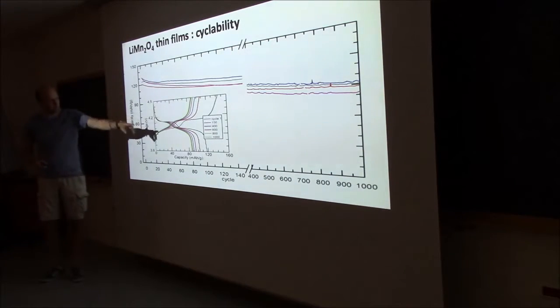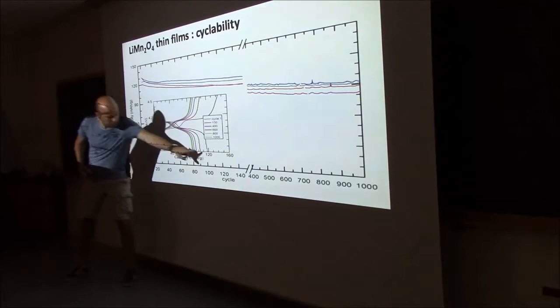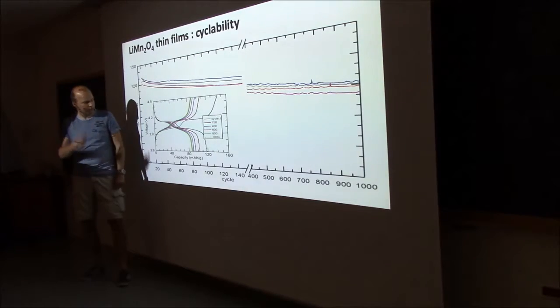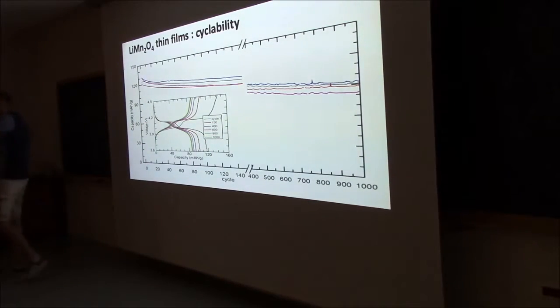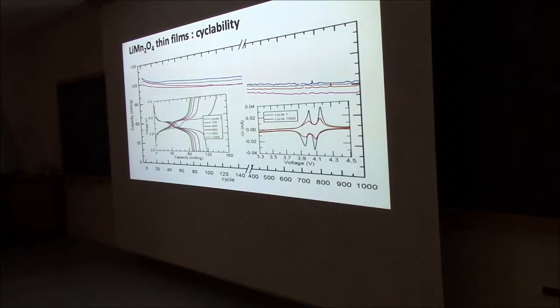Now for these materials, if you cycle them, you can see the discharge capacity goes down over time, which is normal, that's what you see there, but you can see the plateaus are not changing. So always the same voltage that you're taking out. And you can also see that in the CV measurements, where the first cycle had a very strong peak, the other side of the peak dropped somewhat, but you can see it didn't move, so the internal resistance wasn't changed. I'm not showing it over here, but we also do a lot of electrochemical impedance spectroscopy, so that you can study your system and you can really extract all the different components which are contributing to the impedance, from the ionic conductivity, electroconductivity, all the different things, which is not simple. You can do the measurements, but then to make a model which explains this, we're pretty lucky that we have an expert in the group who is retired, but not really retired.